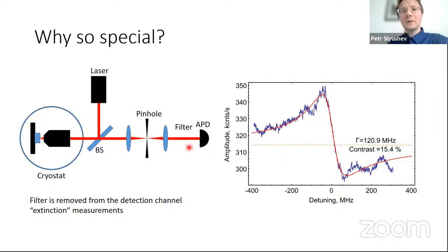If we sweep it, this shape would depend on the distance between the defect inside the diamond and the surface from where light is reflected. So, of course, depending on this distance, you can acquire different phase, and therefore this picture can have a negative resonance, positive resonance, and everything in between, like, for example, on this picture.